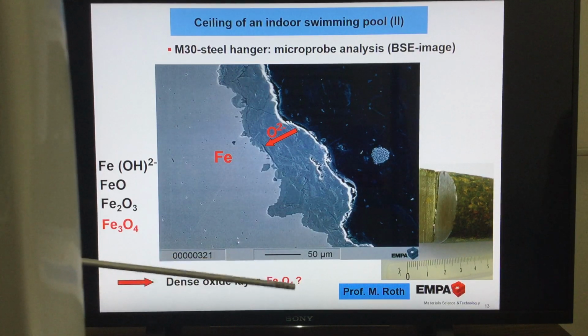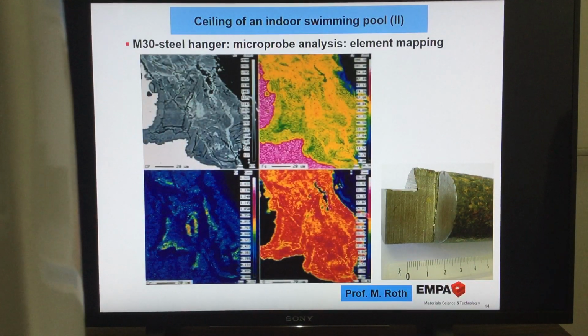And this we can easily measure. Just to show you, this is a backscatter electron image here, and in the same machine, in the microprobe analysis, we see the distribution by mapping. That is for the backscatter image. That is for iron, the distribution, sorry, and this is for chromium. Of course, there's chromium in the oxide layer, and also the oxide. That's oxygen.